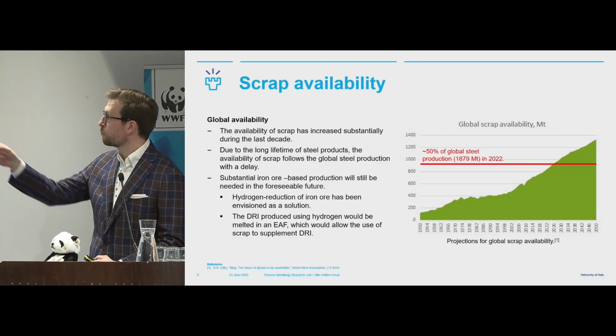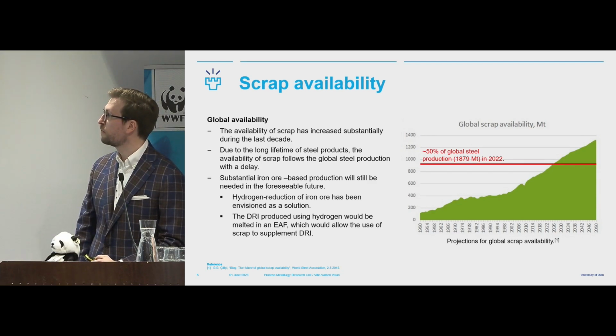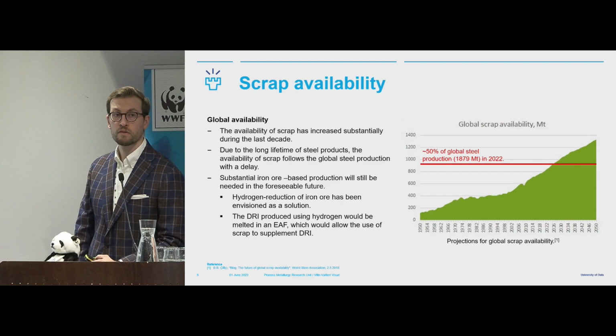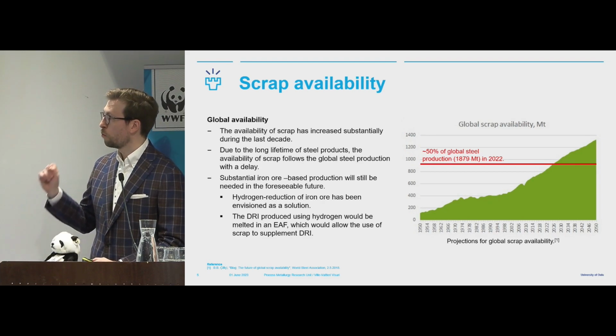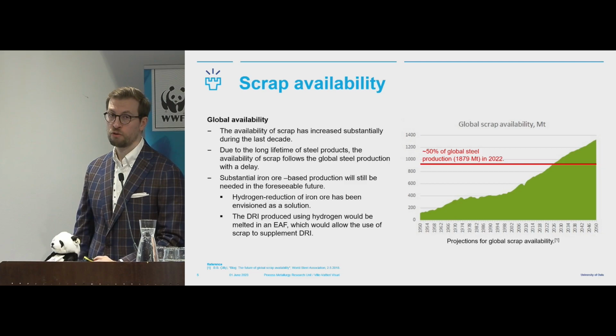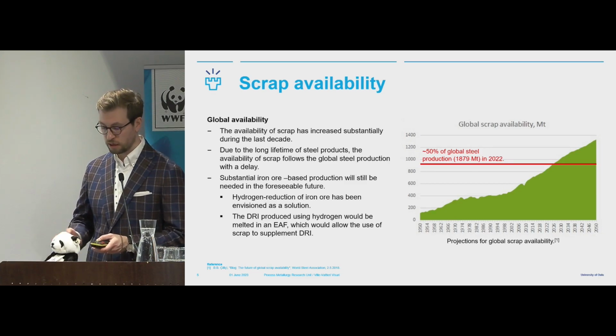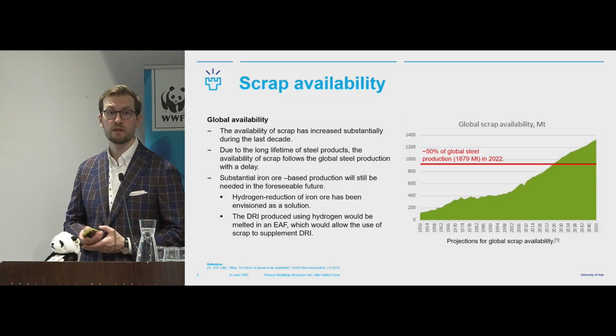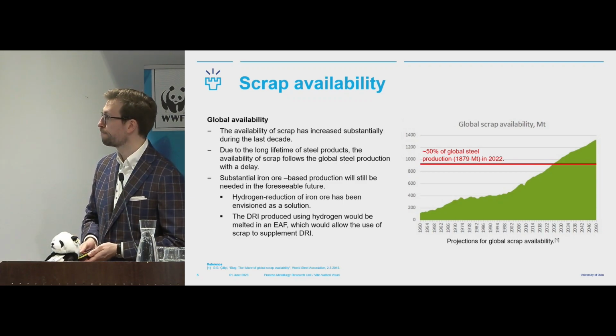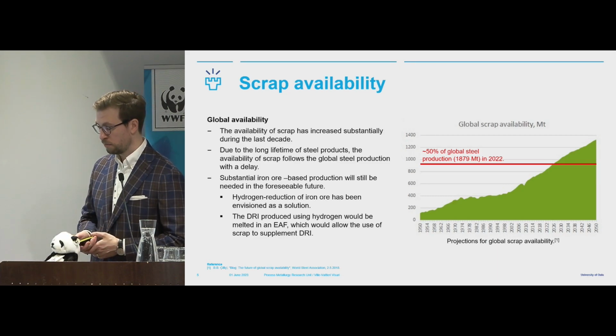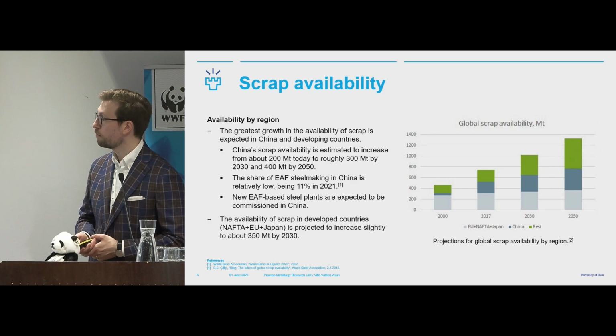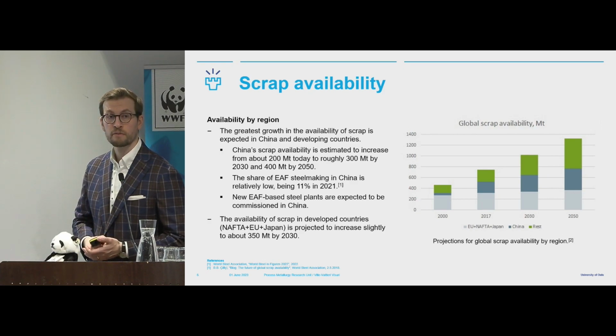seriously behind. And I put here this red line, which indicates 50% of global steel production in 2022. So we see that we are not really even there yet at the moment, but we will be catching up. What this means in practice is that we will need to have also substantial iron ore-based production. The question is how to organize this in a way that doesn't produce as much CO2. Probably we could use hydrogen. And this is from a process technology point of view very interesting, because we will be using electric arc furnaces to melt this direct reduced iron.